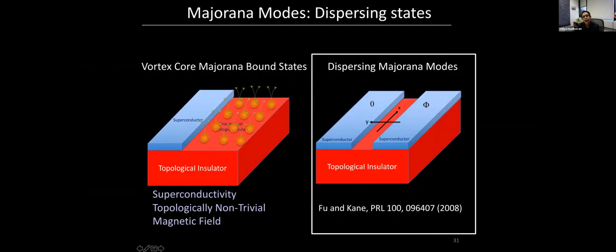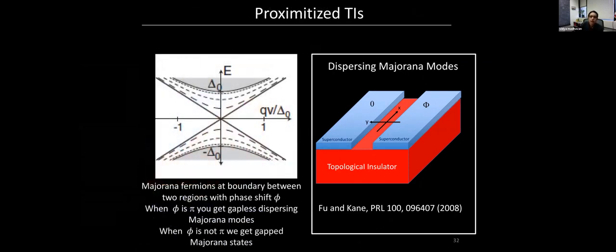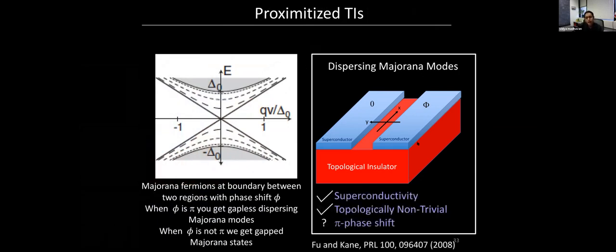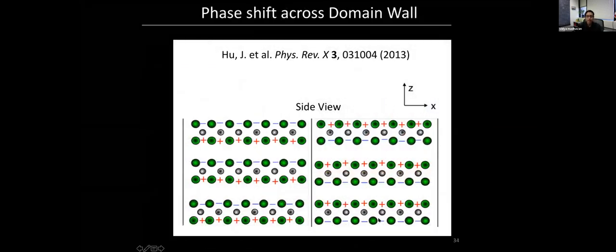Now, in my lab, when we started looking at FeSeTe, this was a while ago, these pieces of evidence were not there. So we were very interested in asking the question, can we find any other evidence that this material is topologically non-trivial? So one thing you can do is look for signatures of these propagating Majorana states. And we have superconductivity. We know this is topologically non-trivial, at least now we do. I think there's enough evidence. The third ingredient you need is a pi phase shift.